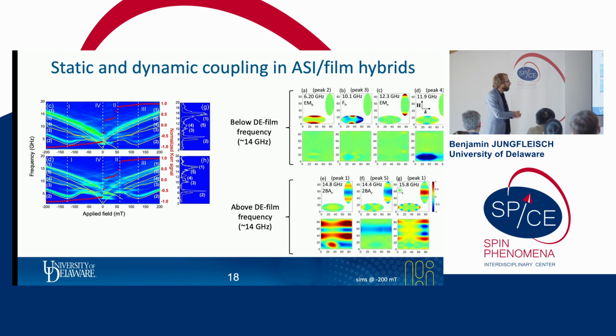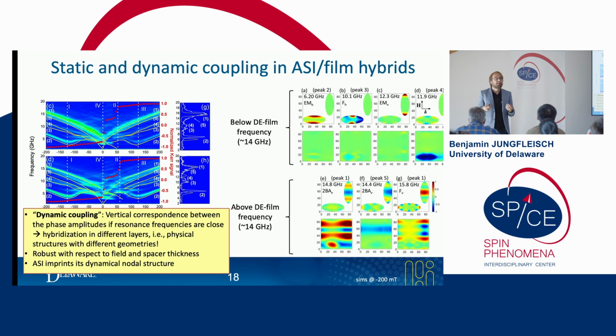And we can also see here for 15.8 gigahertz, this is more like a bulk-like mode. And if we now compare the spatial mode profile between the artificial spin ice and the film underlayer, there is an out-of-phase correspondence between the two. So we can have both in-phase and out-of-phase modes in the system, basically acoustic and optical modes. So this dynamic coupling is a vertical correspondence between the phase amplitudes in the two different layers. So this leads to a hybridization in the layers. I'm not going to show you that, but this effect is robust with respect to the film thickness and the magnetic field. So the artificial spin ice imprints its dynamical nodal structure in the film underlayer.